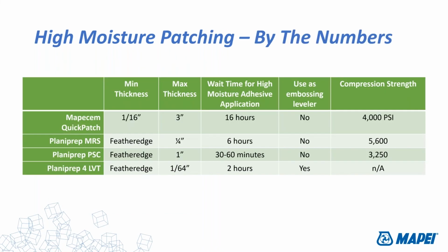Okay, so anyway, by the numbers, let's take a look at all these products and how they compare. Again, Mapecem QuickPatch, minimum thickness is a 16th of an inch over the highest spot. Max thickness is 3 inches in small areas of 24 square feet. You have to wait for about 16 hours before you can apply high moisture adhesive on top of that. And you cannot use an embossing leveler, but it's a very strong and high compression strength product.